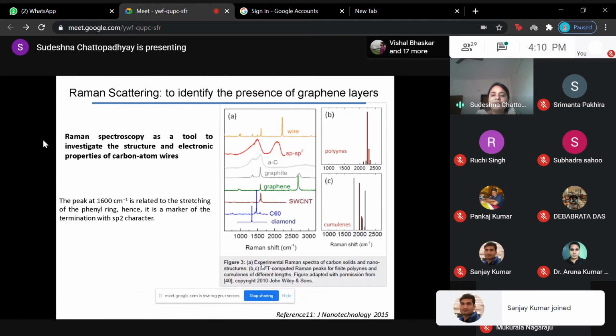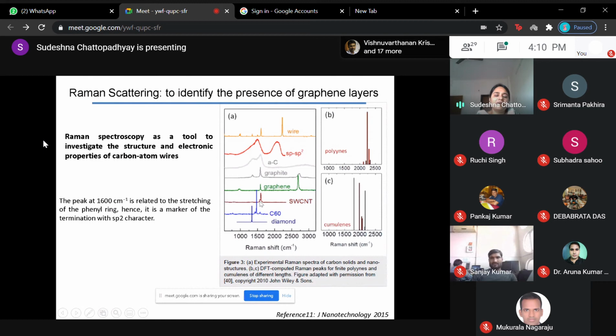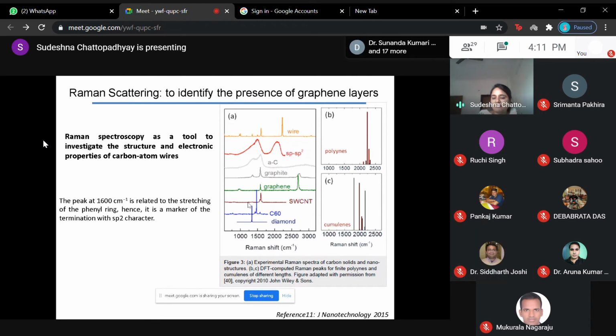From some papers you can see that for carbonaceous material the G peak will always be there close to 1500, but how the D peak and other peaks change differs. They have shown Raman data for different carbonaceous materials: graphene, graphite, carbon nanotube, diamond, and fullerene, which is again carbon 60. So this is how your 2D peak and the D peak change. That is a kind of fingerprint test. Looking at the data, you can tell whether this is the signature of graphene or just some carbonaceous material. That has also been verified from a theoretical model. This is a reference paper where they have shown that.